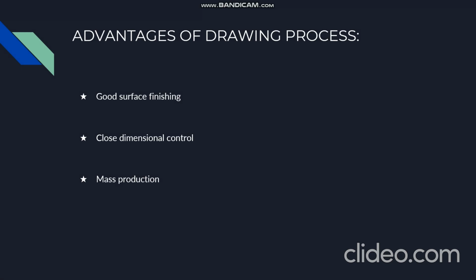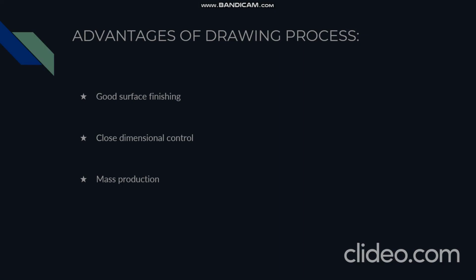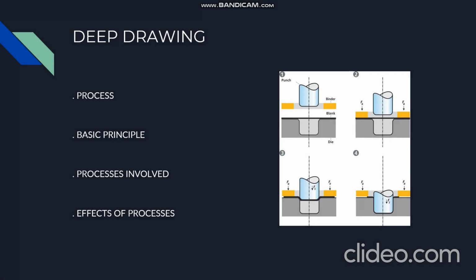This process slows down the flow of the sheet while it is drawn, thereby preventing wrinkles from forming under the binder. The punch stretches the sheet over the die radius and forms it in the die, and the amount of punch force necessary for forming thereby continually increases up to the lower dead center of the punch.